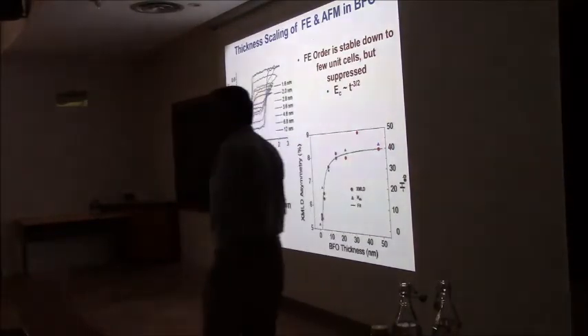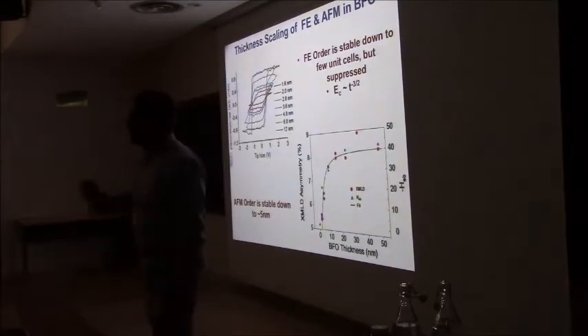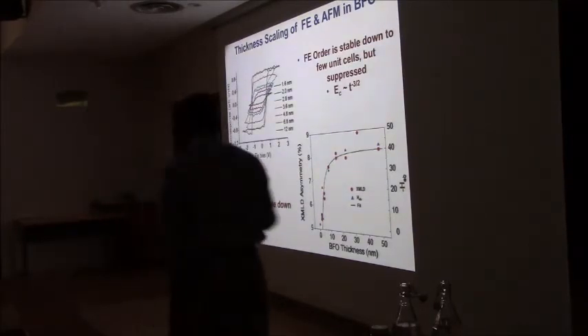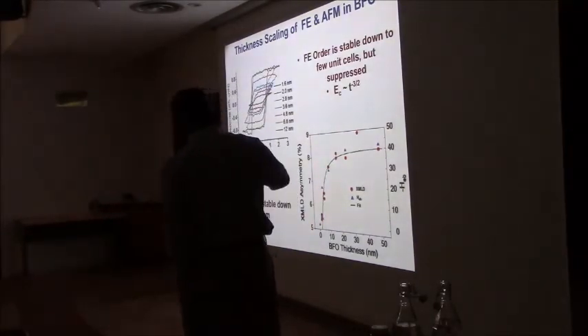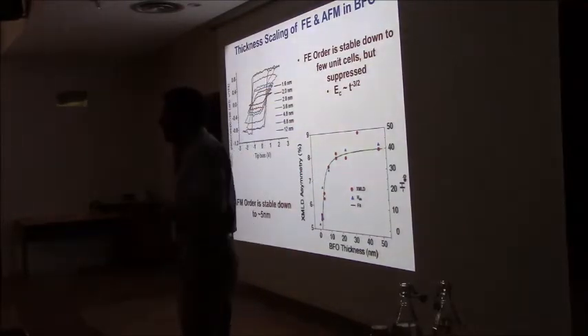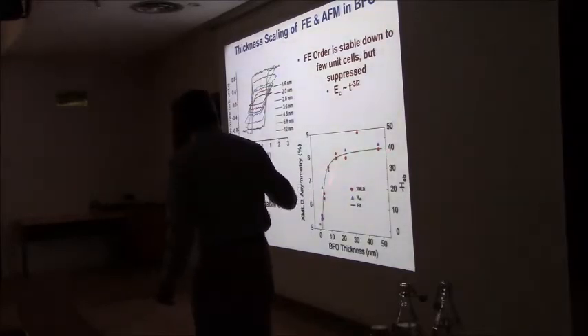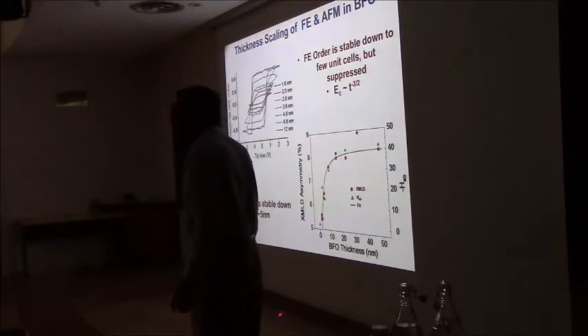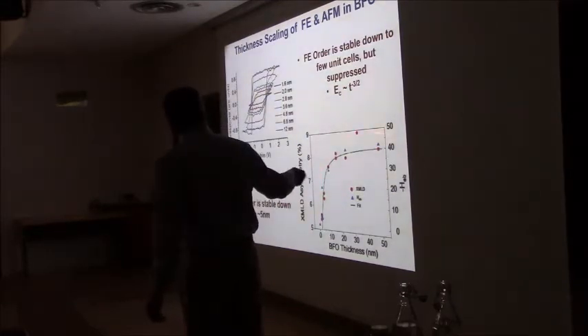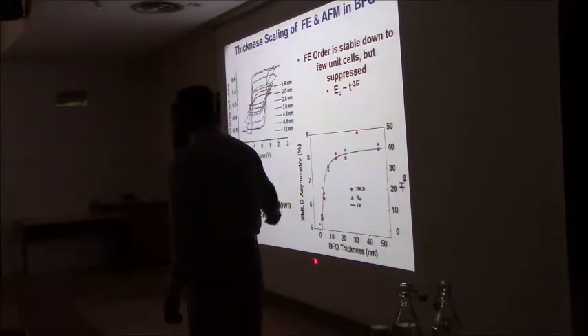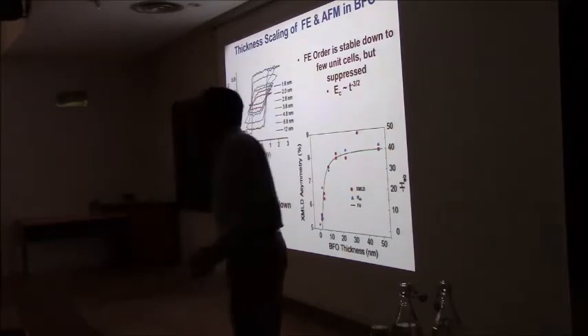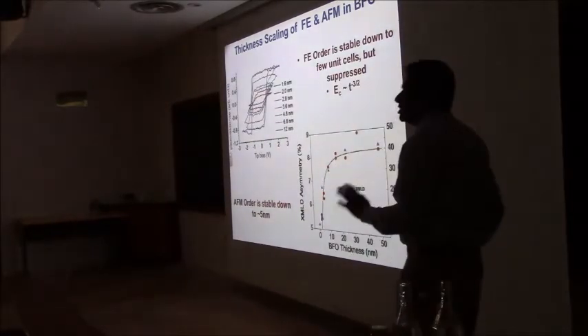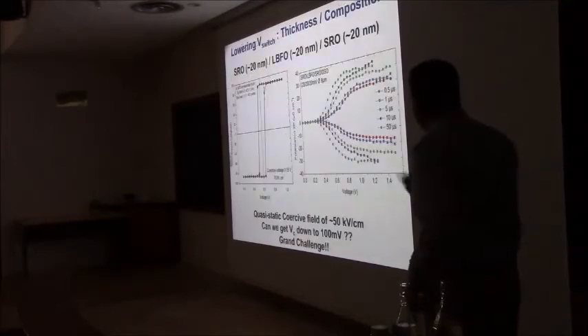On the magnetic side, we know that the antiferromagnetism is quite robust, at least down to 5 nanometer thickness, tens of unit cells. And that's X-ray magnetic linear dichroism, which measures, in some sense, the strength of the antiferromagnetic order. It says that it is stable down to about 5 nanometers or so. Then it starts to get suppressed. This data also has exchange bias coupling to a ferromagnet, and they both say the same thing, that indeed antiferromagnetism is relatively stable down to at least a few nanometers.